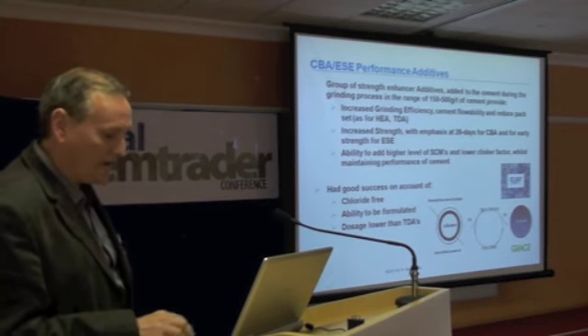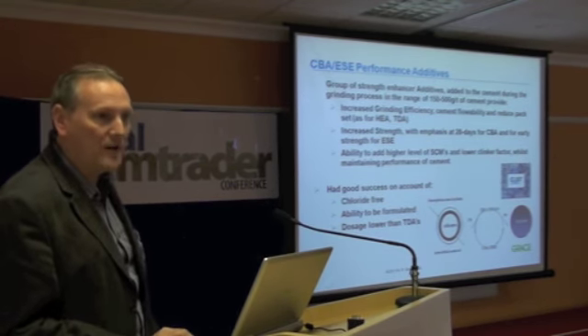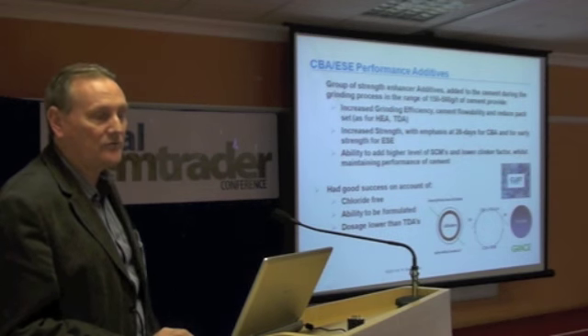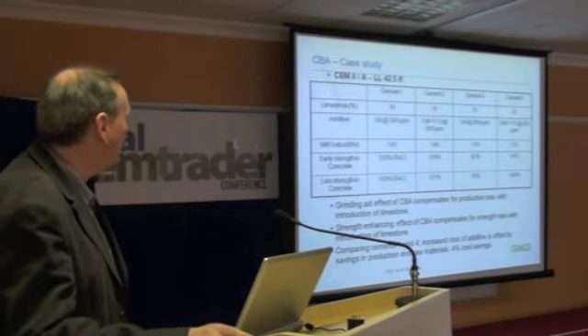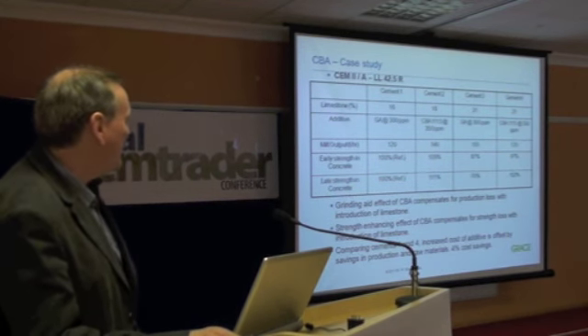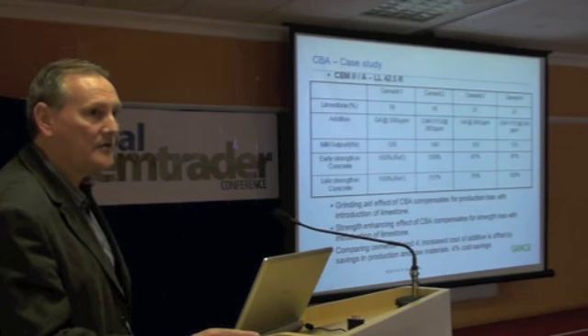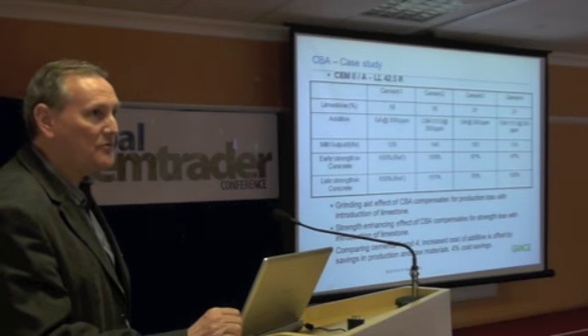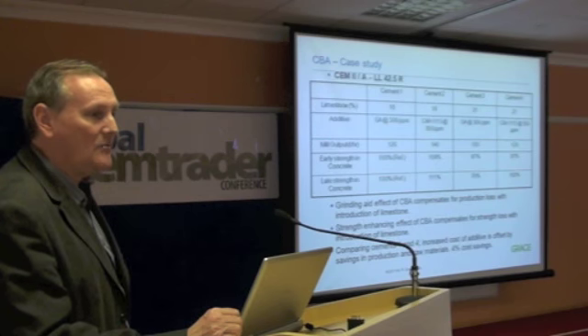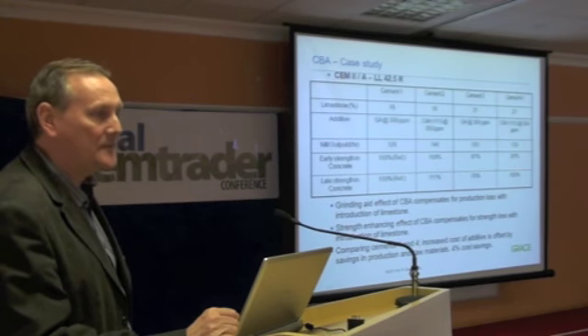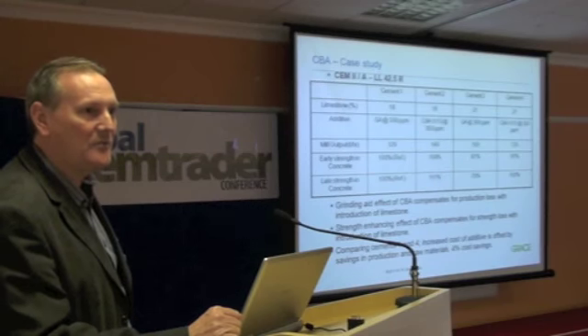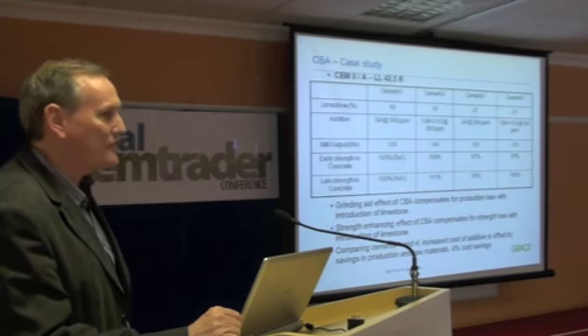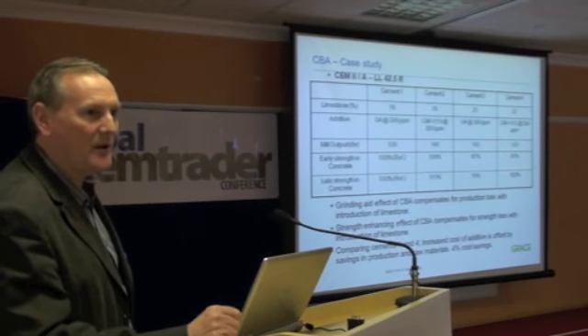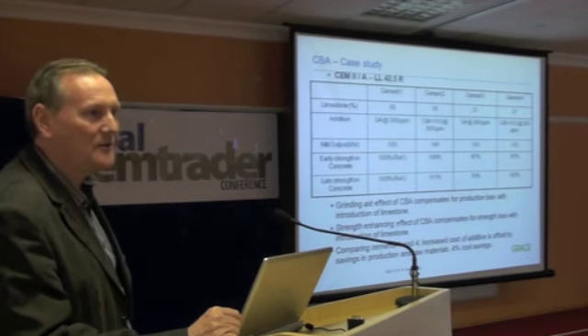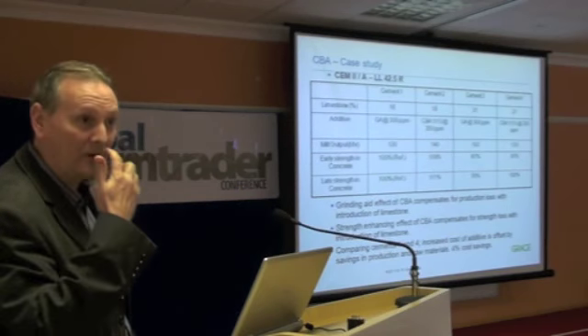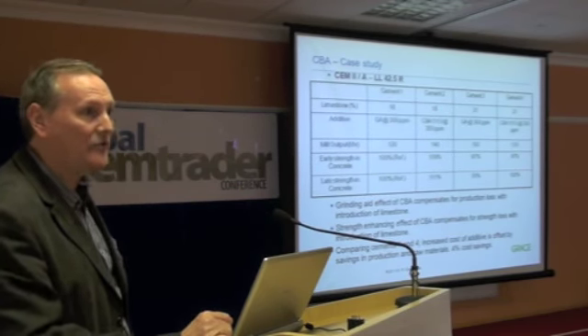But we understand some of the mechanisms enough to be able to choose the right kind of chemical recipes to put together which make our products. And a quick example here with the limestone cement, and yesterday I know we focused on slag and fly ash. In simple terms, slag and fly ash are more expensive than limestone to a cement producer, but they're more beneficial on the cement performance. So it's more or less true that the cost per megapascal is much the same whether you use limestone or slag or fly ash, because the limestone is much cheaper, but it has a much stronger negative effect on your performance.